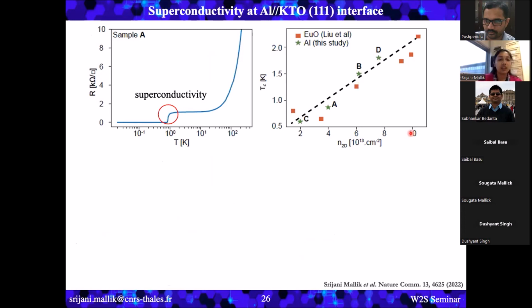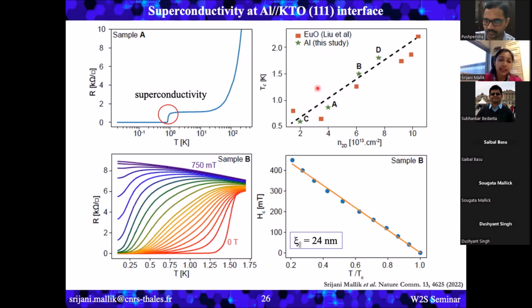And then when we did the transport measurement, we found superconductivity in our sample also. The superconducting Tc can also be tuned by varying the growth parameters of the samples. And the scaling of the superconducting Tc with respect to the carrier density matches very well with the one reported by Liu et al., which is the first paper related to KTaO3 (111) superconductivity. And then we studied the critical field associated with the superconductivity. By fitting this data using the Ginzburg-Landau equation, we calculated the coherence length, which came out to be 24 nanometers, a similar order of magnitude as found by Liu et al.